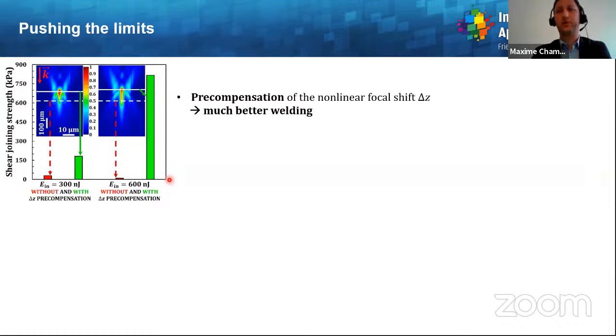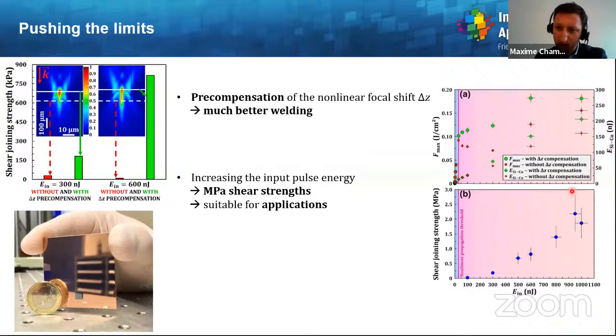Okay, so now the main question is, can we simultaneously keep this precompensation of the nonlinear focal shift delta Z strategy and increase the input pulse energy to get even more energy deposition at the focus? And the results are essentially shown here in the bottom. So the shear joining strength as a function of the input pulse energy, and you can see that around 1 microjoule input pulse energy, one can reach around 2.2 megapascal shear joining strength, which is quite suitable for applications.